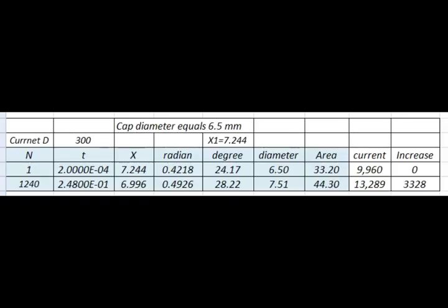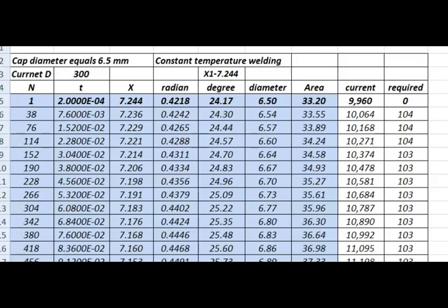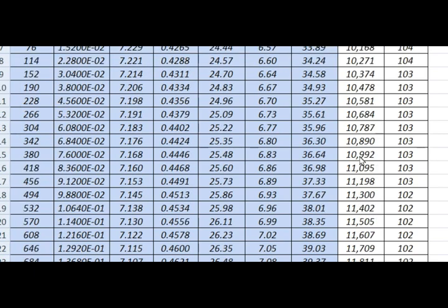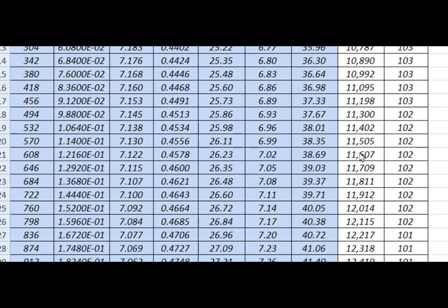We can build a spreadsheet using this information. The 300 is the current density, and 7.244 is the distance between the 6.5 mm surface and the center of the weld. At weld 1,240, the area is 44.30 square millimeters and the current is 13,289 amperes. In this spreadsheet, current increased every 38 welds, and the blue shaded area is the number of welds versus area. All you have to do is multiply the current density by the area. You will get the exact current at that weld in order to keep current density constant.